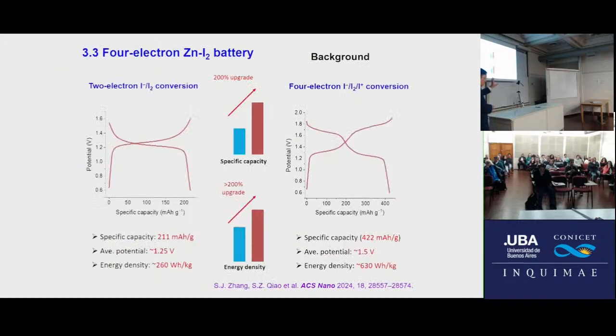Okay, so the third method, we need to consider increasing energy density. We just mentioned compared with the lithium battery, the battery energy density is a little bit low, right? We must consider increasing energy density. We just introduced two works, but those two works are based on the 2 electron conversion. This means iodine minus to iodine 0, this conversion. In that case, capacity is 211 only, and energy density is 260.